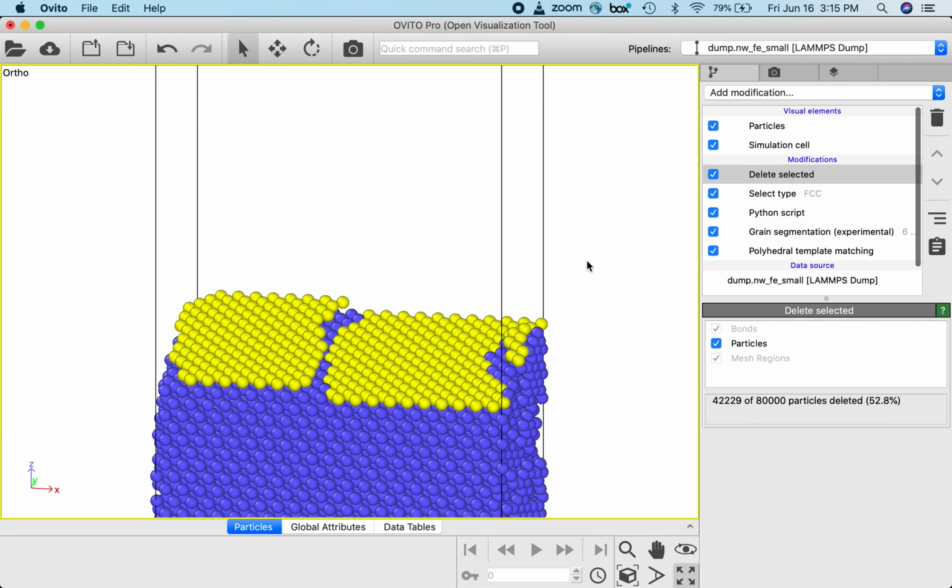So this is a very important step. You have to find coincidence site atoms, or DXA has to. If it can't find any, or if it only finds a few that are very far apart, it's not going to work. So you can't proceed on to actually do the line defect. So that is kind of the main drawback of DXA, is that it requires that these CSL atoms be detectable.